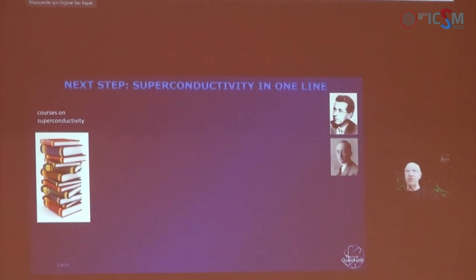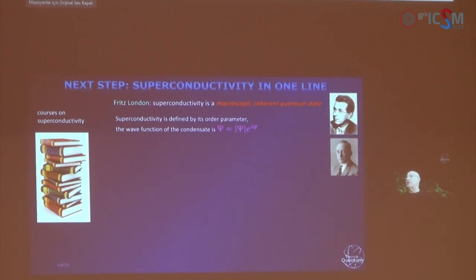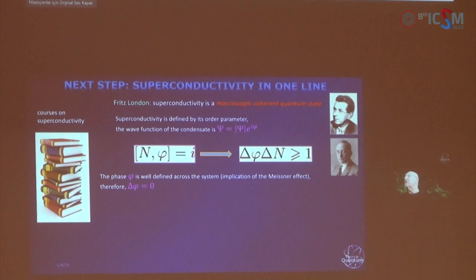So basically we have a lot of courses on superconductivity, careful and beautiful, but what we will try to do is to understand superconductivity in one line. Basically, in one line, we use the beautiful Ginzburg-Landau concept that superconductivity is a macroscopic coherent quantum state, and therefore should be defined by the order parameter, which is nothing but the wave function of the superconducting condensate. Then we use the uncertainty principle, which relates the uncertainty in the phase and the uncertainty in the number of particles, meaning the uncertainty in the amplitude of the parameter.